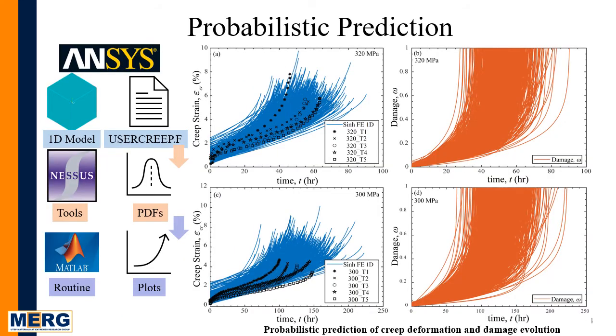This slide contains the probabilistic prediction for the 1D model. So we took the 1D model and updated the user creep in the finite element settings. Then we used a probabilistic tool in ANSYS to map the random responses for each of the sources of uncertainties into the ANSYS input deck. Then the simulations are conducted in ANSYS. Then the results are processed through a MATLAB subroutine, and all these probabilistic predictions are done for the creep deformation and damage evolution.